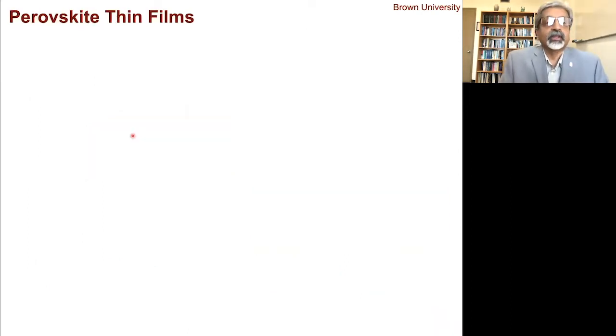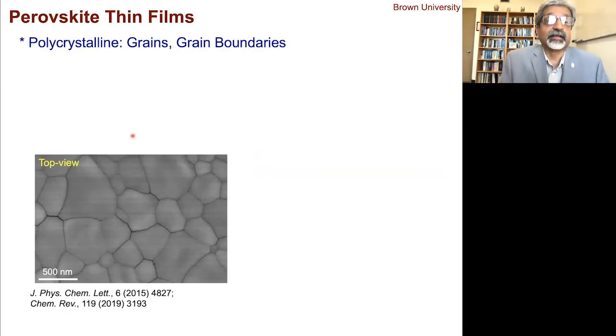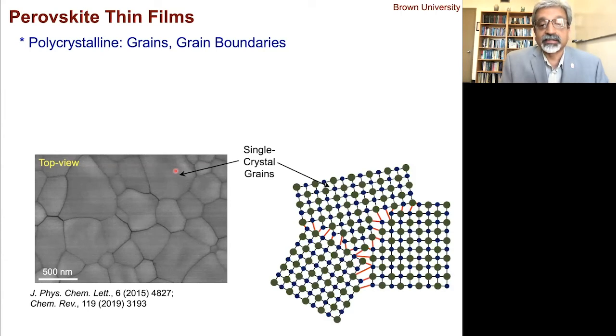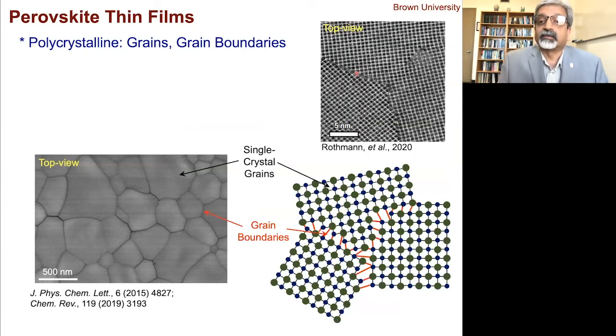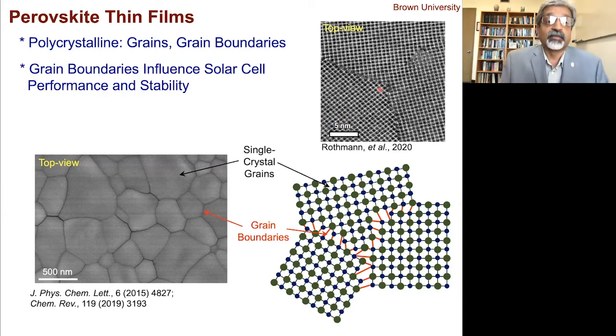Okay, so here's the perovskite thin films. They're polycrystalline, as I mentioned, so they have these grains. These grains are single crystal. And then these are grain boundaries where the grains actually meet. This is actually a micrograph from Rothmann, which basically shows the atoms and the grain boundaries. This is a high resolution transmission electron micrograph. So the grain boundaries actually influence solar cell performance and stability quite dramatically.